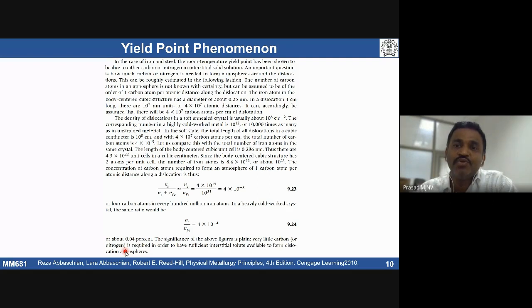So soon after annealing, before fabrication, one has to subject this material to a small amount of reduction, typically around 1 to 2%. That's where we see a uniform, constant stress strain. There is strain at a constant level. That much strain you have to give so that you can follow the regular trajectory of a stress strain curve of the material.